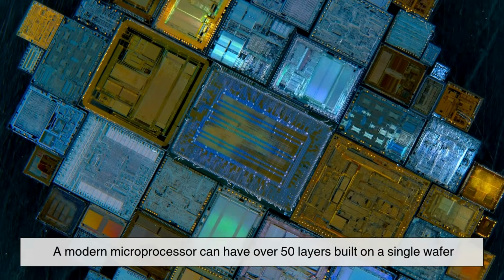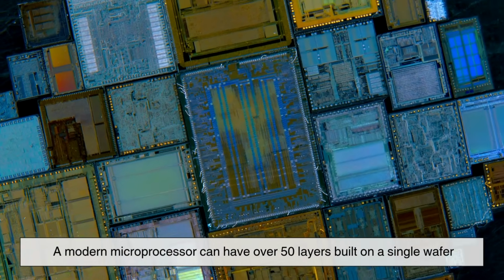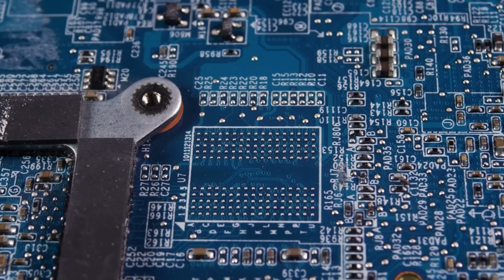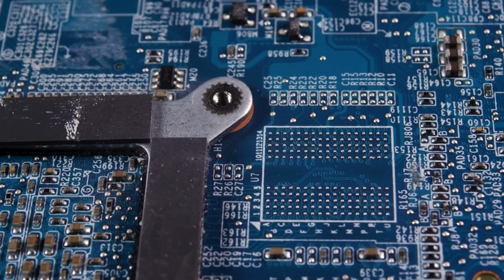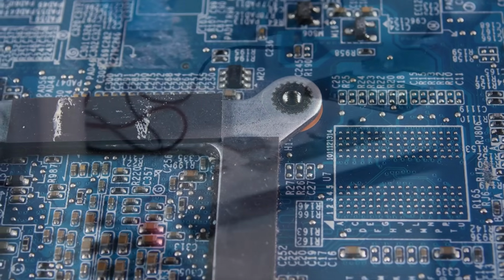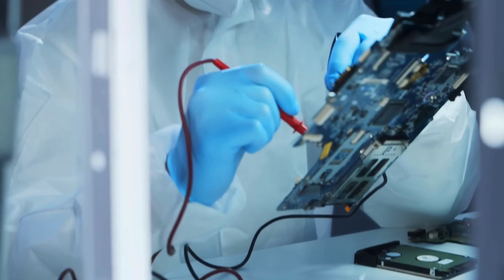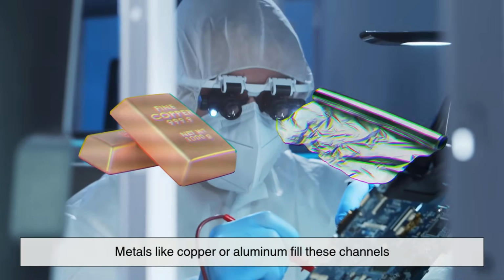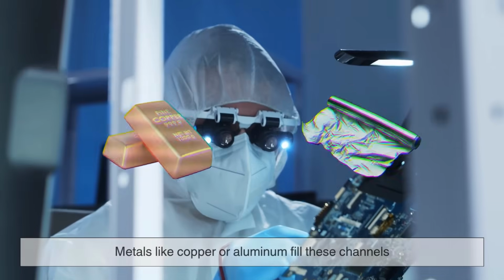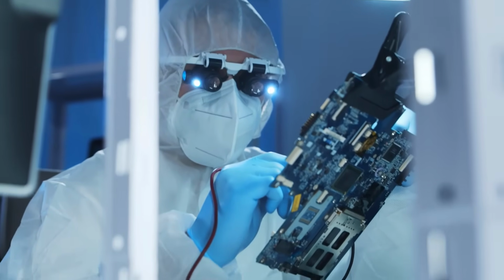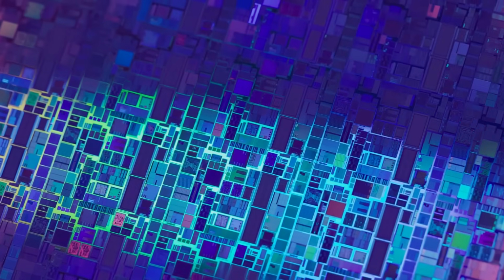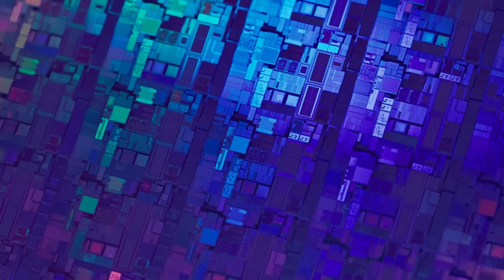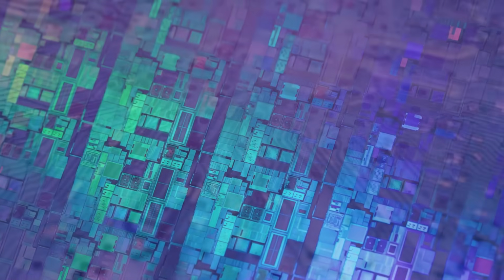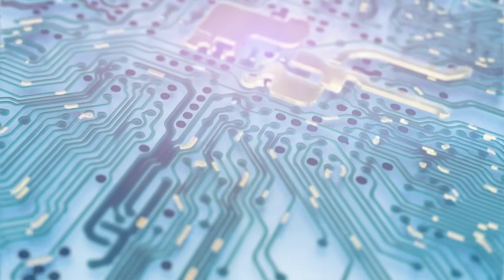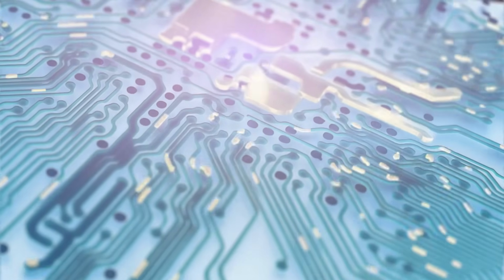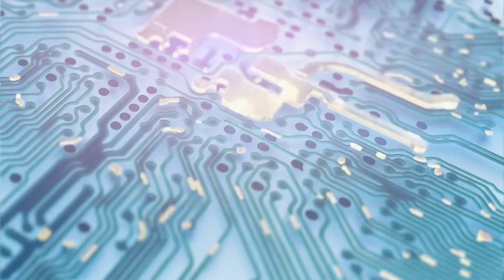A modern microprocessor can have over 50 layers built on a single wafer. Between circuit layers, we deposit insulating materials, usually silicon dioxide or low-k dielectrics, then open vias, holes, so metal wiring can connect different layers. Metals like copper or aluminum fill these channels, followed by chemical mechanical polishing to ensure a flat surface. Each layer demands another photolithography, etching, and deposition cycle. The choreography of hundreds of these steps in the correct order takes weeks, even months of fab time for a new technology node.